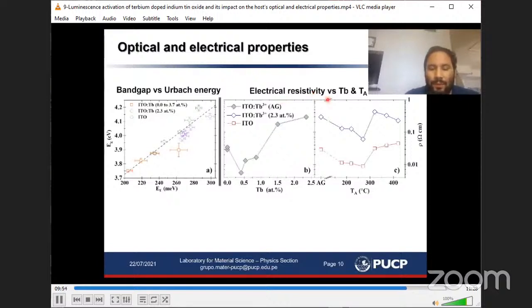Also, we perform four-probe measurements, or van der Pauw measurements, on samples with no thermal treatment but different terbium concentrations. For a small amount, of course, we observe resistivity larger than the typical resistivity one obtains on ITO, in particular due to the growth conditions. We grow these samples by cooling down the substrate holder. But very interestingly, we see also, in agreement with the optical analysis, that for small amounts of terbium in the host, there is a reduction of the electrical resistivity.